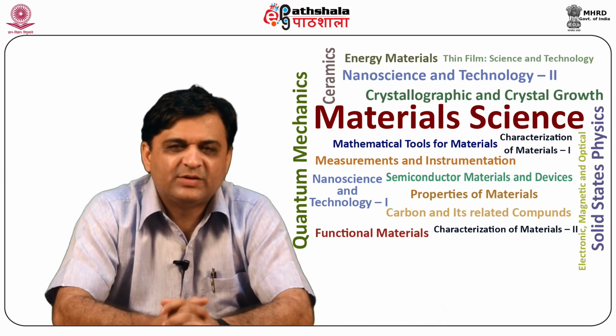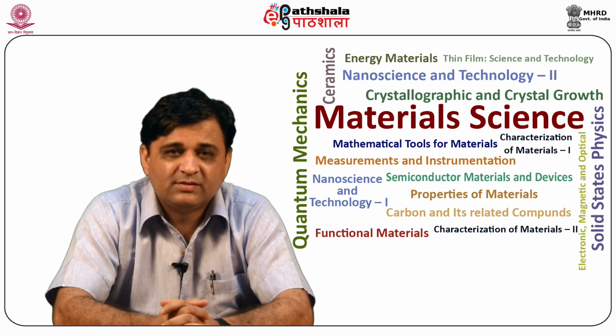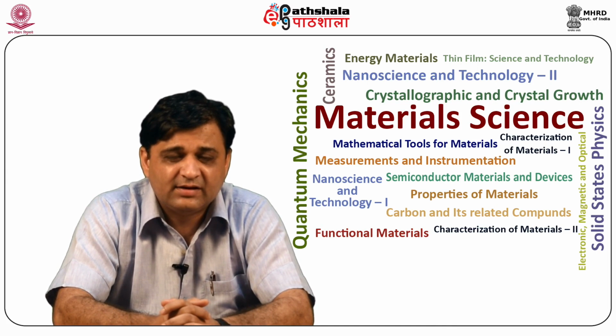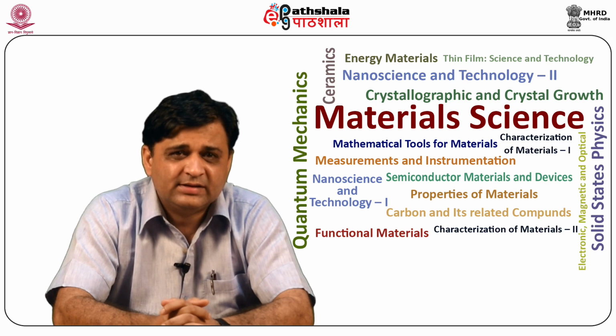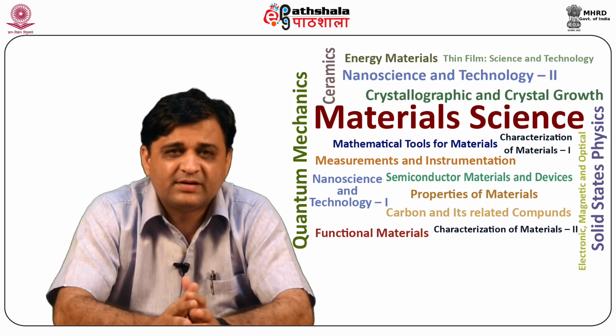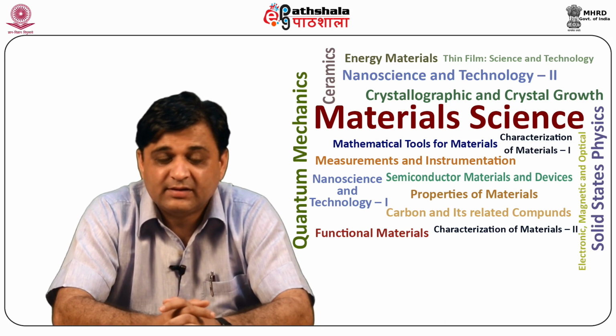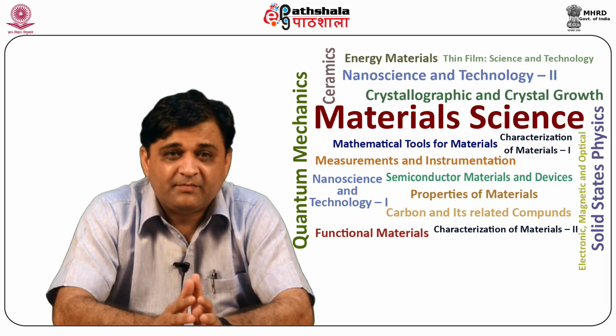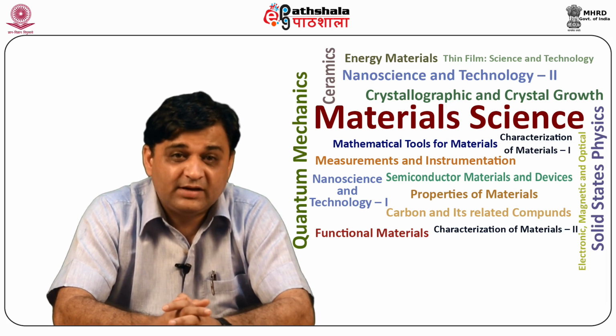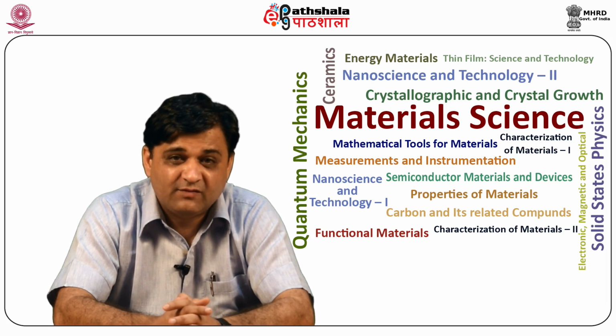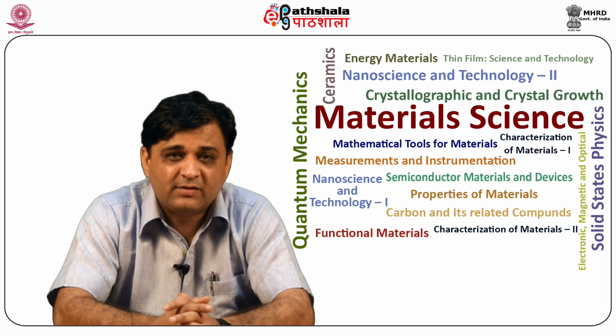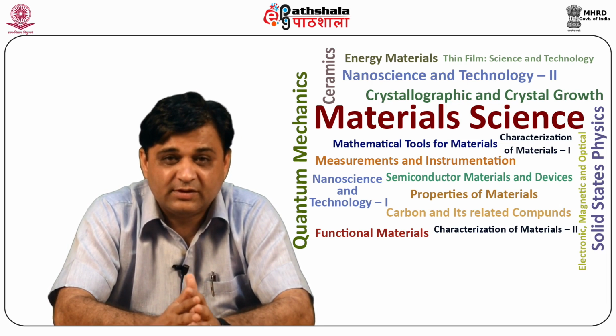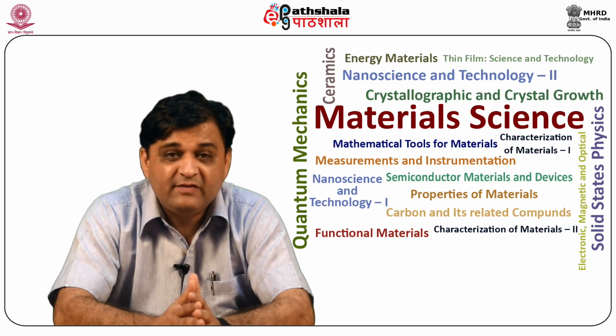So students, let's summarize what we have learned in this module. When X-rays fall on a surface with an incident angle smaller than the critical angle, total external reflection occurs, which makes it a surface sensitive technique. We also learned that the reflectivity of a flat surface falls as the fourth power of the wave vector transfer, and for a rough surface it falls even faster.